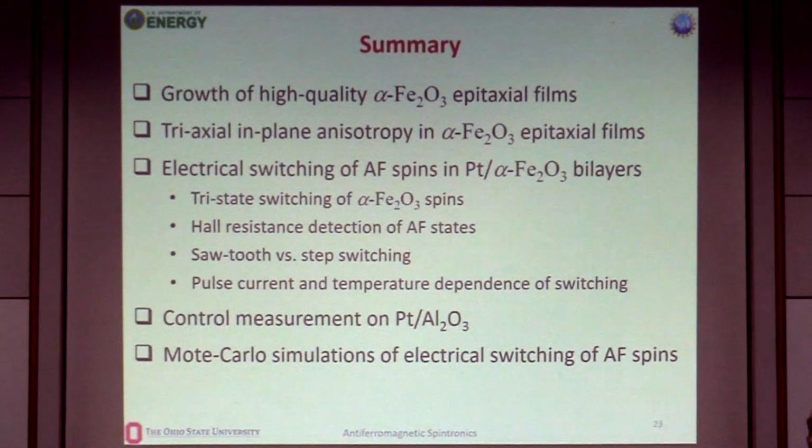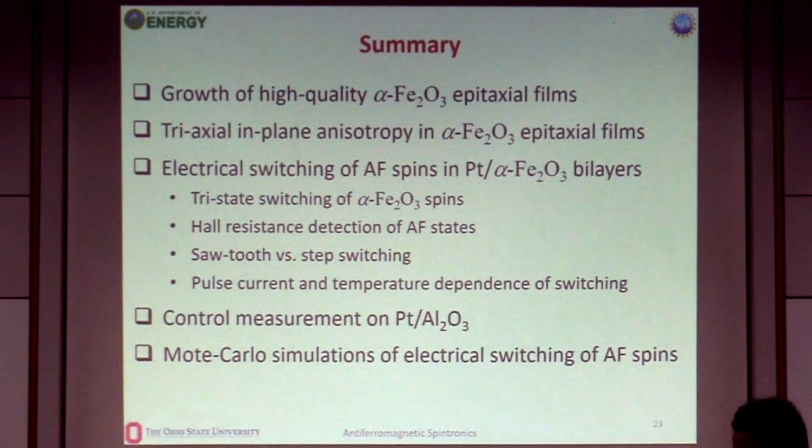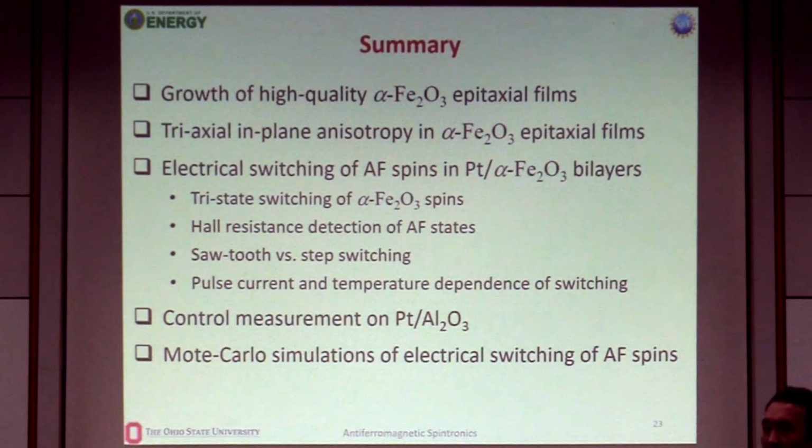So this especially depends on the anisotropy. For example, when I switch to YIG, this biaxial YIG, this is also one-step switching, because the anisotropy of this iron oxide is quite small. So the switching is one step, at least from one easy axis to another easy axis, I believe.